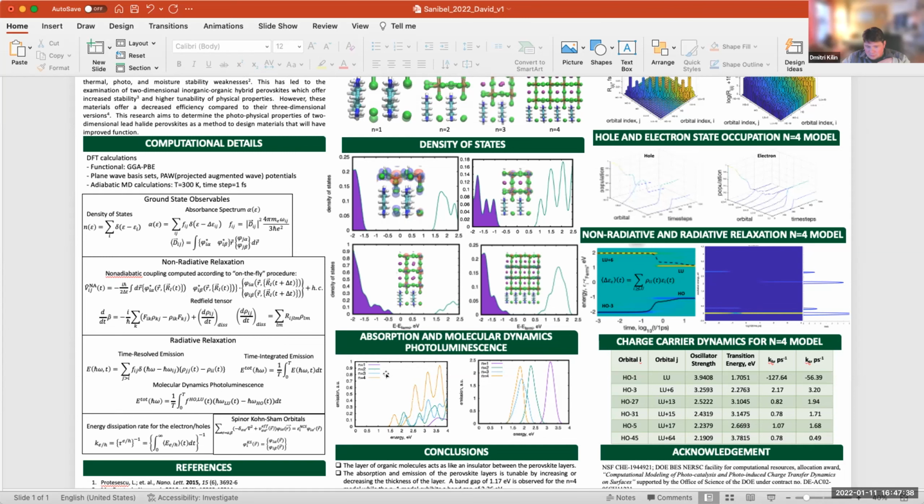So it's quite trustable. I wouldn't emphasize the word DFT. There are much more precise methods, but general electronic structure calculations for absorption are reasonable. And even if they're not super precise, they give a good prompt of which range of the spectrum one may expect properties in, if the material is novel.